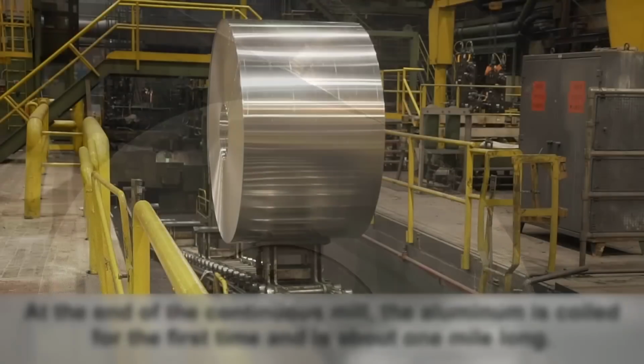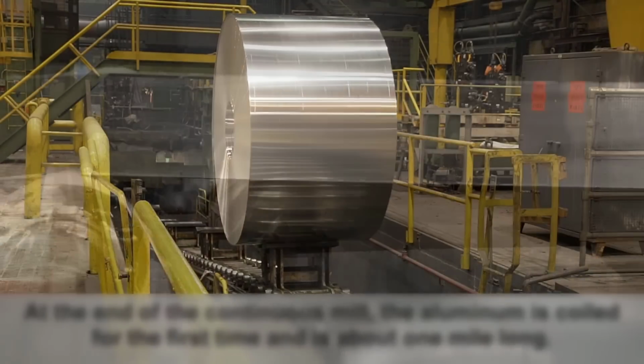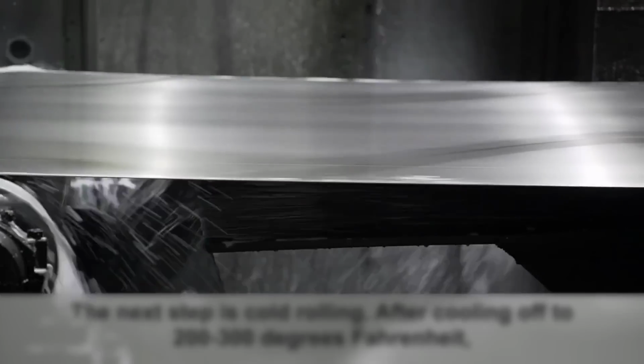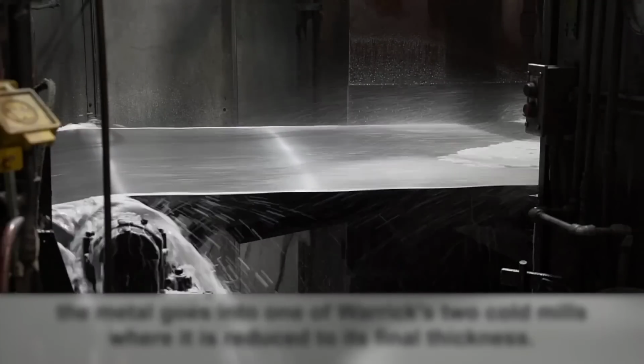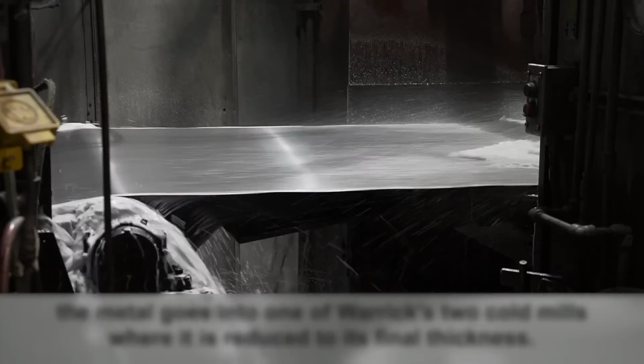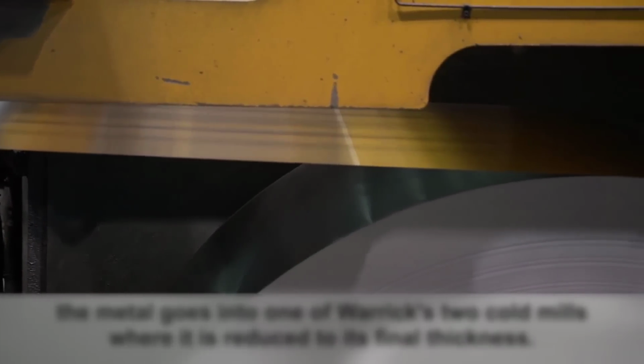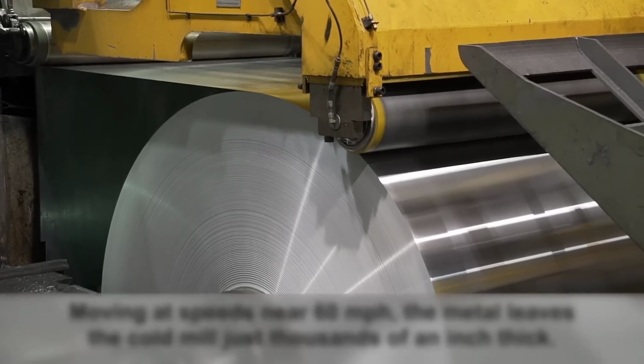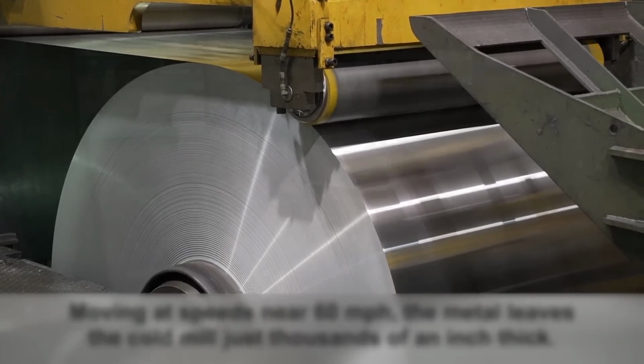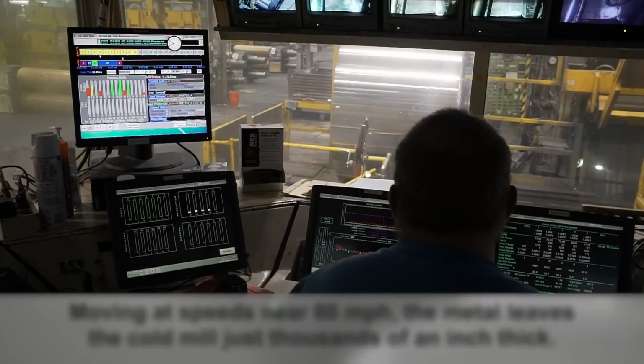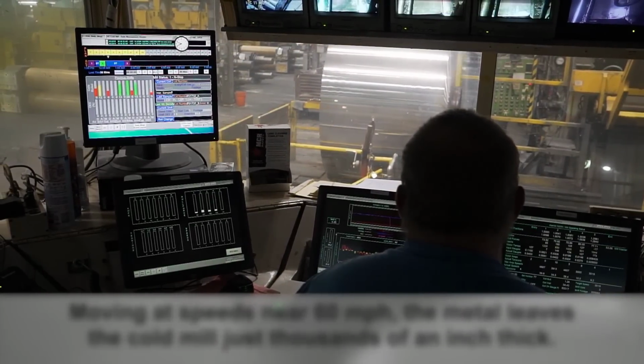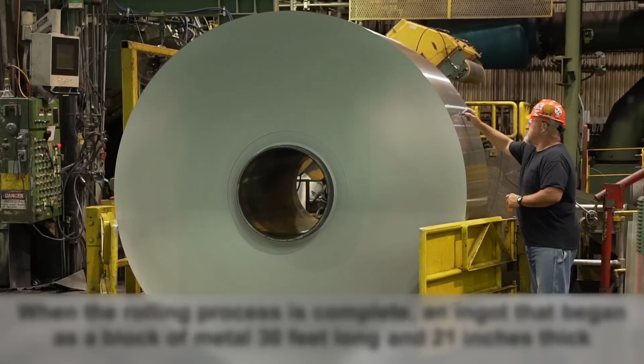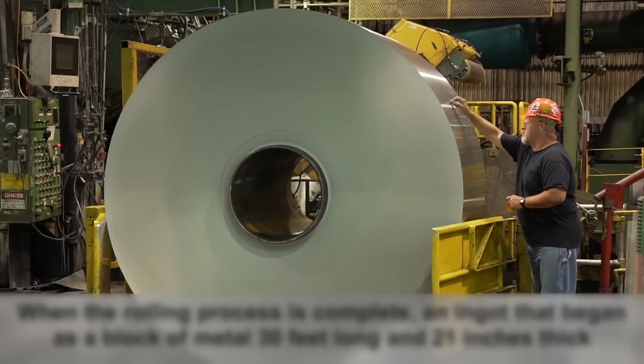The subsequent phase, cold rolling, takes place after the metal has cooled down to temperatures between 200 to 300 degrees Fahrenheit. The aluminum proceeds to one of Kaiser Warwick's cold mills. In this environment, the metal undergoes further reduction in thickness, all while traveling at speeds nearing 60 miles per hour. Exiting the cold mill, the aluminum reaches an incredibly thin dimension, measured in thousandths of an inch.